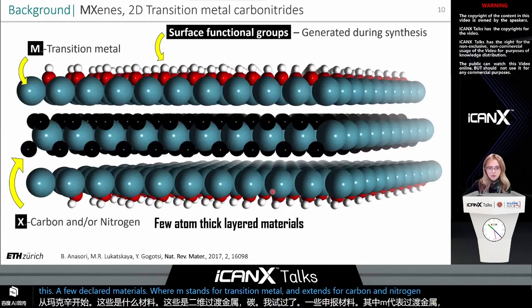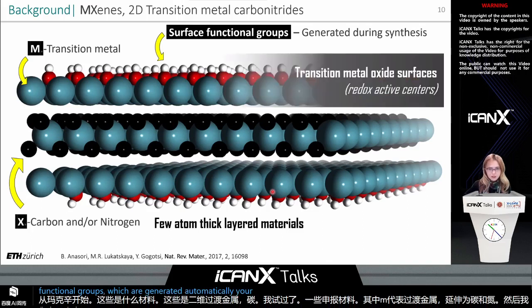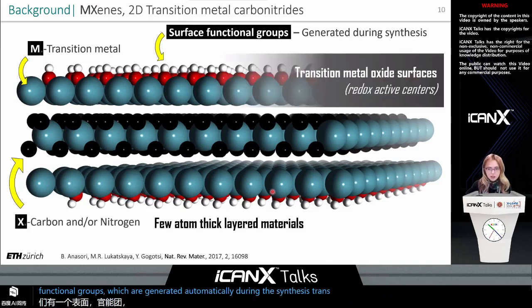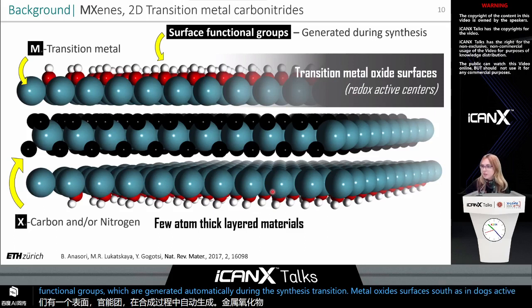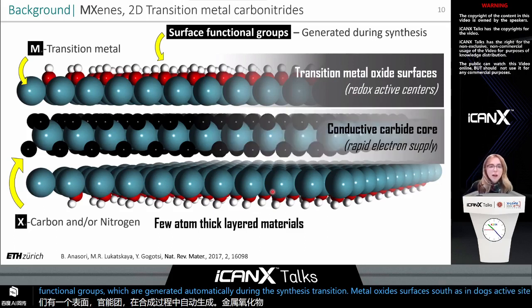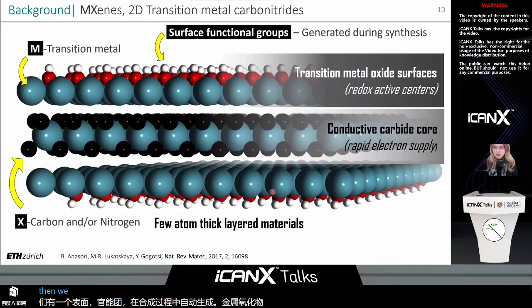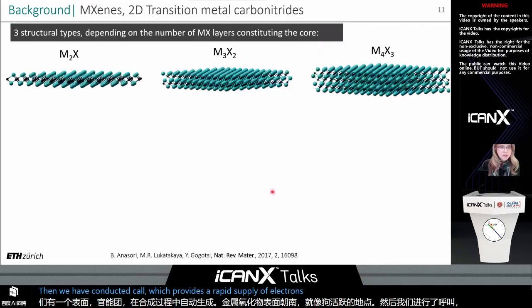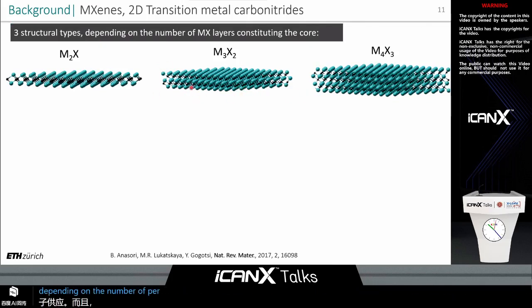And then we have surface functional groups, which are generated automatically during the synthesis. Transition metal oxide surfaces serve as redox-active sites. Then we have a conductive carbide core, which provides a rapid supply of electrons. There are also multiple structural types that we can select from, depending on the number of MX layers constituting the core.